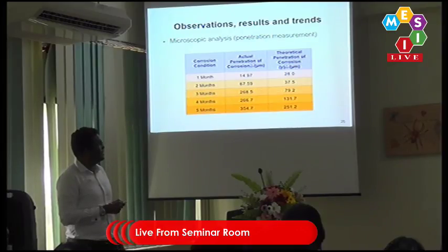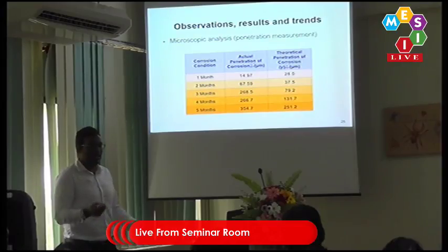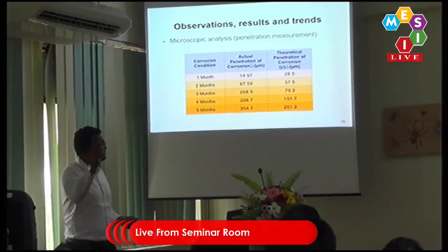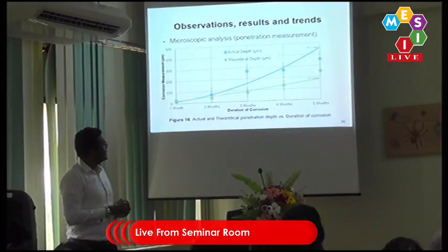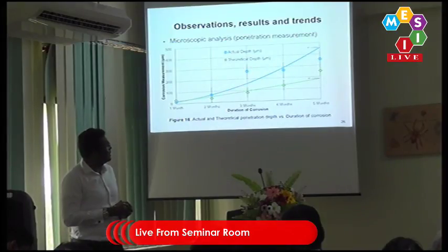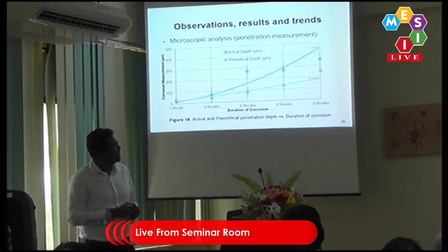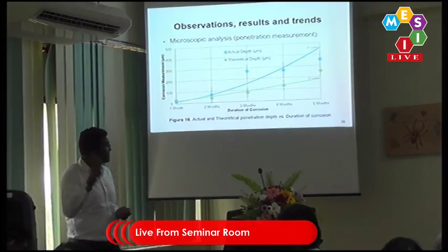I think the third month is rather anomalous, but that is to be expected because the corrosion pits are local and this is not a foolproof method. And this is the sort of comparison of the two curves. You can see that it is due to this data point that the graph sort of deviates massively. It would have gone much closer to the green curve otherwise.